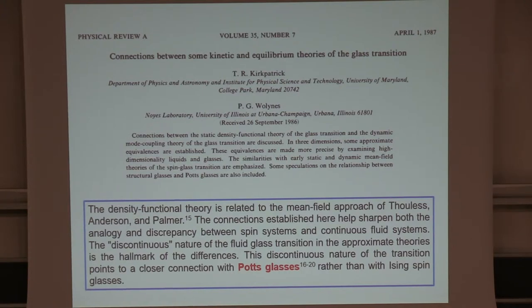So that didn't solve anything, except in the meantime, Gross, Kanter, and Sompolinsky had solved the Potts spin glass that we heard about, and they had this very strange phenomenon of having a discontinuous phase transition, but nevertheless one that had no latent heat, for example, which is true of glasses. So we suggested in this paper that the discontinuous nature of the transition points to a close connection with Potts glasses rather than with Ising spin glasses.